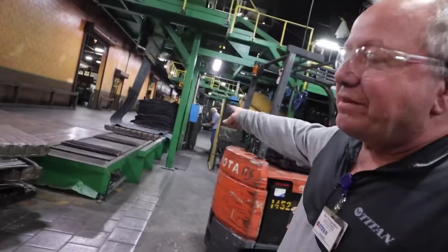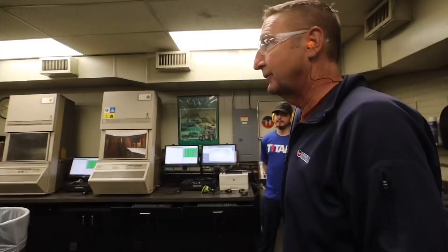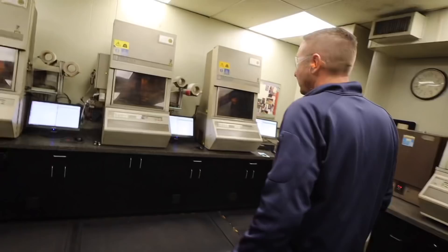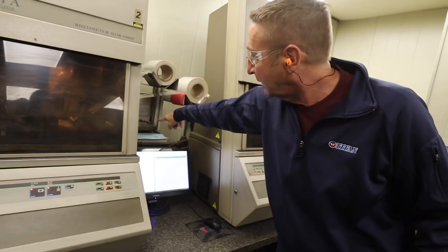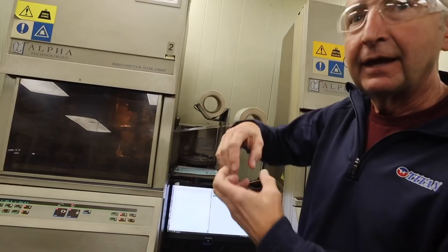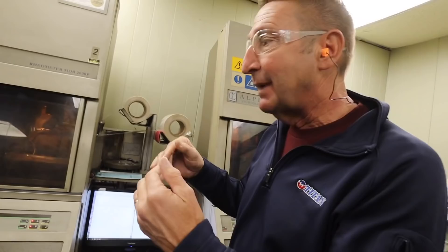This is coming out productive now. He'll take seven samples for every skid. All those samples come into what's called a rheometer. What this machine does is there are two dies that come together — we take the sample of rubber, it feeds into the machine, clamps down, and those two dies oscillate. As the rubber cures out, it takes more torque to oscillate, and each rubber has its own specific fingerprint that it has to meet certain gates. This is called a rheometer curve or the cure rate. If it doesn't pass, we may have to rework it — like baking cookies, if you don't have enough brown sugar, you can go back and run it through the Banbury again and add whatever was missing.